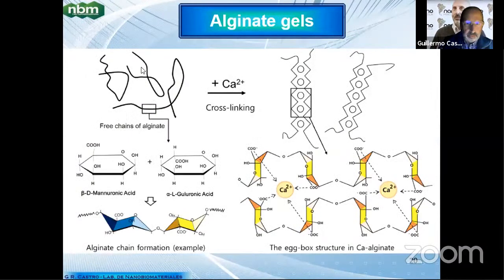So we use alginate, and alginate is composed of mannuronic and guluronic acid. They can be cross-linked with calcium, creating the typical egg-box structure. In such a case, this is a polar environment. They can interact with pectin, and we were thinking about that, to create a hybrid structure that will be more disorganized, but can allow keeping the ciprofloxacin inside.